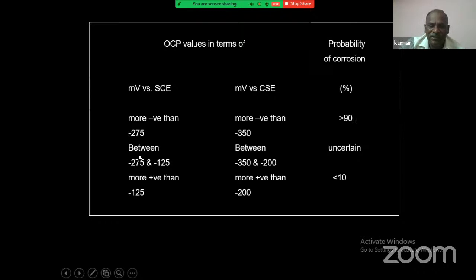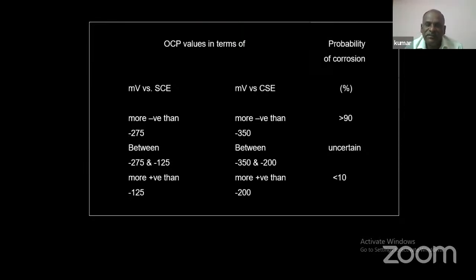If it is between minus 275 and minus 125, it is in the initiation period. And more positive than minus 125, your structure is somewhat better. That means less than 10% probability of corrosion. That means it is okay, it is not corroded at all. So qualitatively, you can make an assessment of your structure by using these open circuit potential measurements.